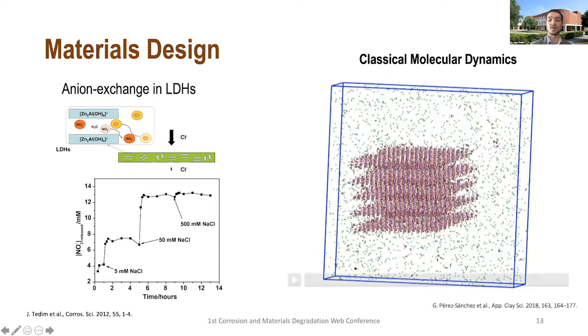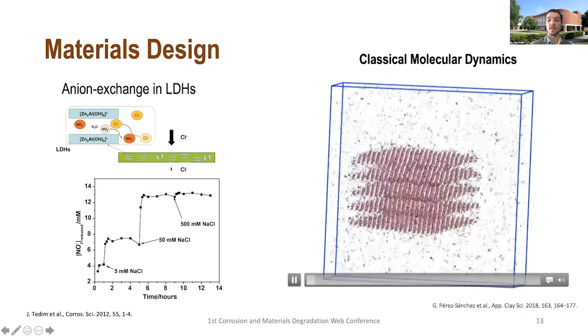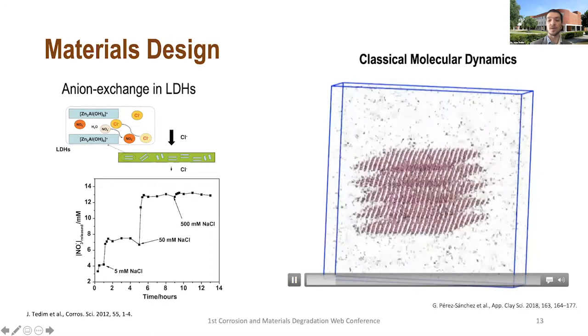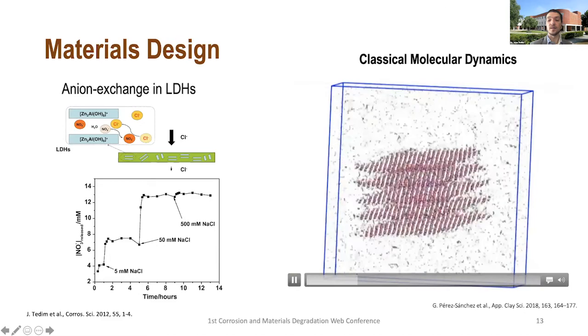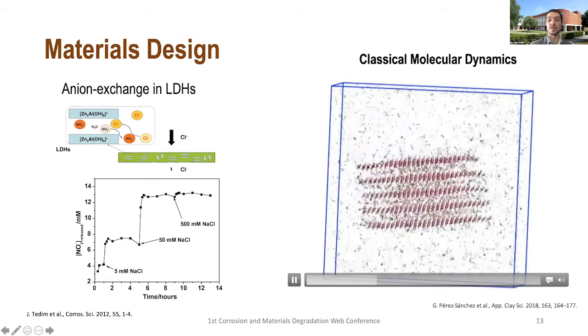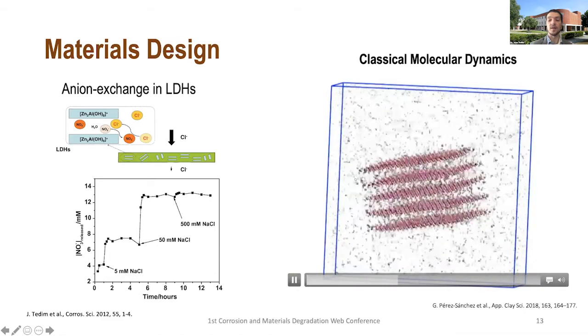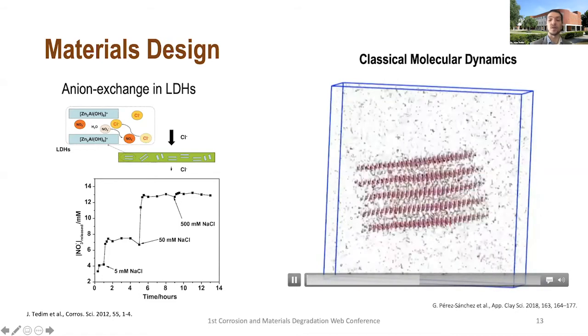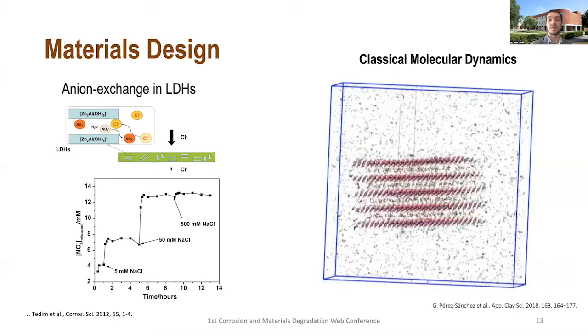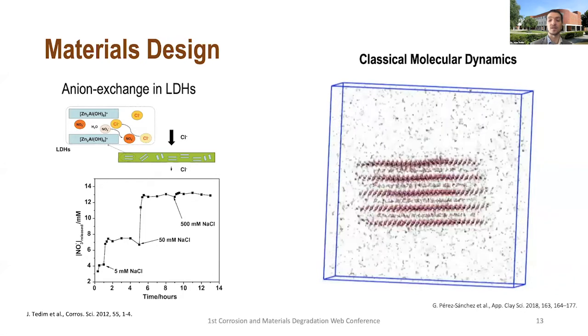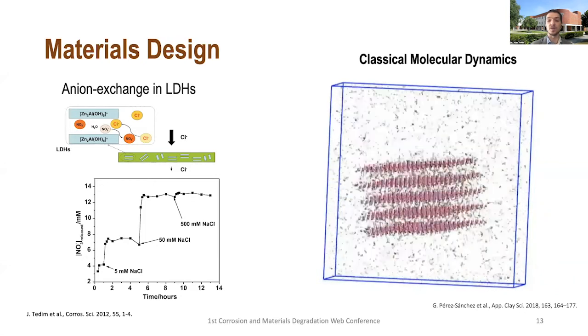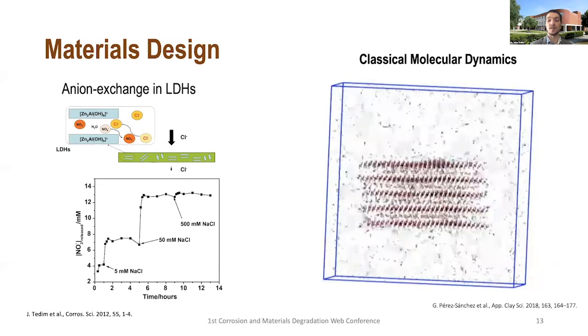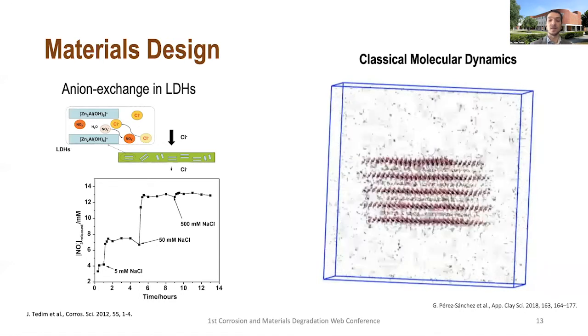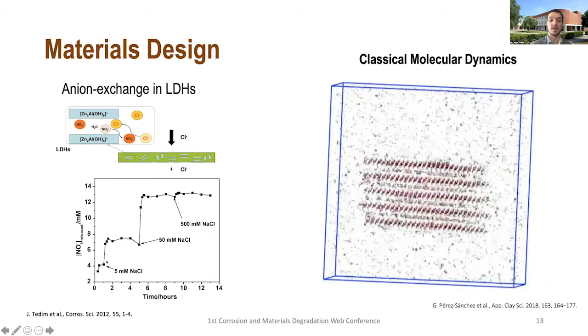And what I'm just showing here is basically a stabilized LDH nanoplate in which we have the chlorides being exchanged on the edges of the LDH on a very short time frame. So we are talking about a nanosecond time scale, and what we are trying to do is increase the simulation time so that we can see what happens in the later stages and approach more the experimental release time scale that we see.